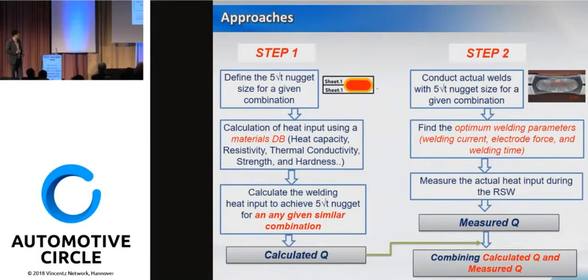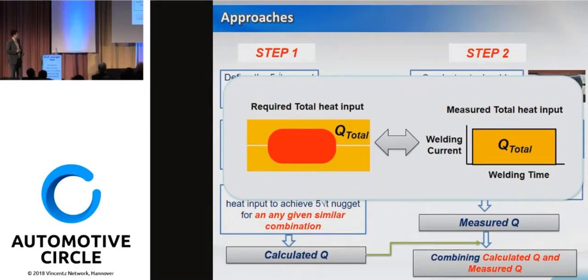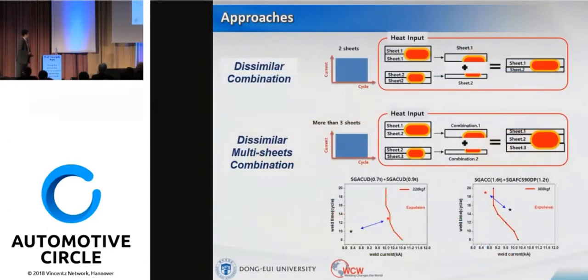And then I adopt this calculated one and combine it with this measured heat input. This is what I do. I calculate the total heat input, the required total heat input for any given similar combination. Then I try to compare each other with the measured total heat input at the specific optimized welding current, time, and electrode force. So if I have measured this total heat input, I can actually calculate back to what the total heat input in calculation is, which means actually I can calculate the nugget diameter as well. So these are my approaches, and another question is what about the dissimilar combination?